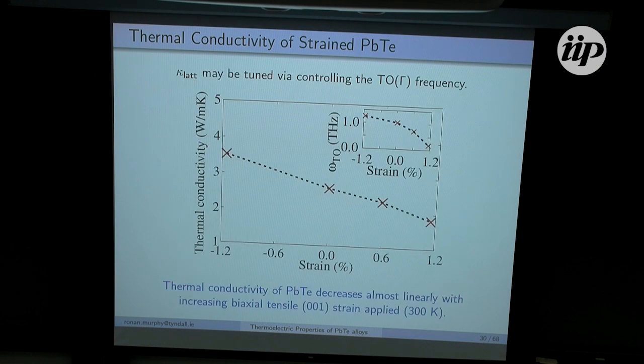But now, just before I move on, I want to talk a bit more about the strain case. So here I have the thermal conductivity as a function of strain. Positive strain is what I've been showing you so far, this tensile 001 strain, and negative strain is compressive strain. And I have here a little inset on the top right of the TO mode frequency at the gamma point. And what you can see here, let's say by pushing lead telluride away from the phase transition, you'll increase the TO mode frequency and get a corresponding increase in the thermal conductivity.